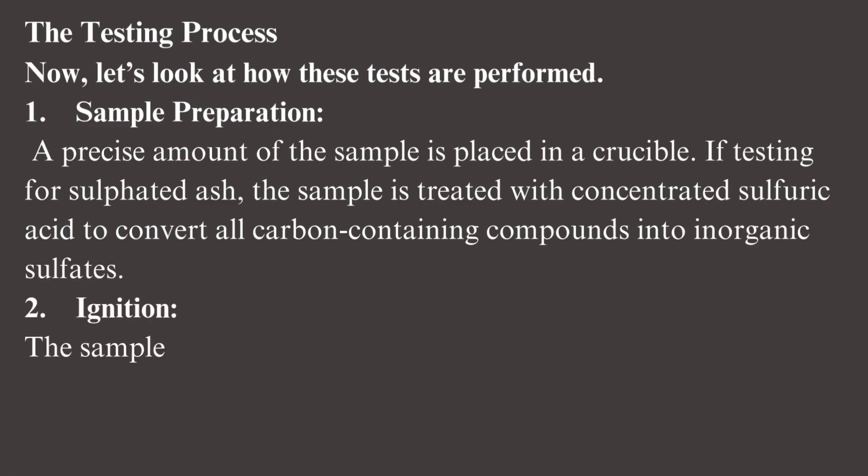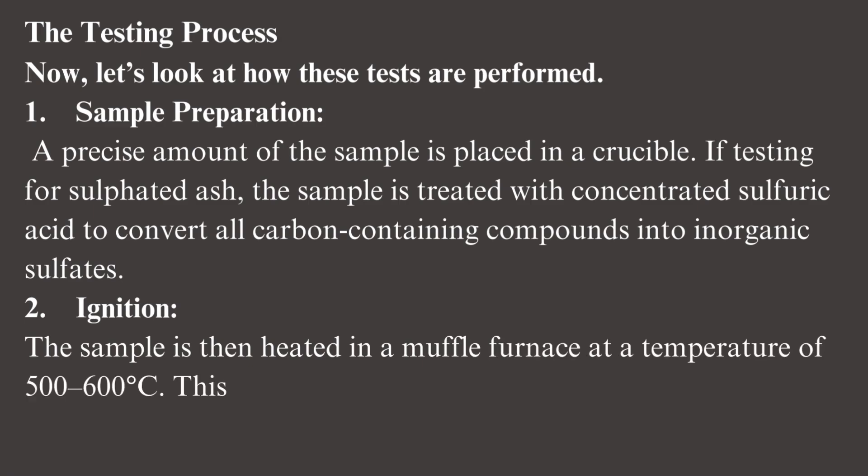Ignition: The sample is then heated in a muffle furnace at a temperature of 500 to 600 degrees Celsius. This step ensures complete combustion of organic matter.